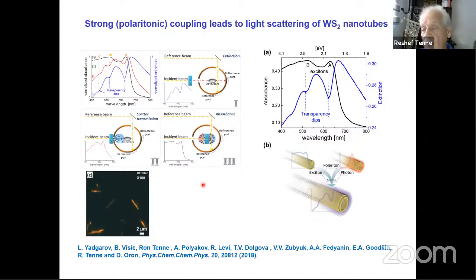As you know, thick 2D materials do not luminesce, but they scatter a lot of light, and we can see this light scattering by forming a polariton. This is a study that was started by my former student Lena Yadgarov, and you see the polariton. If you compare the absorption spectrum of these nanotubes in solution to the extinction spectrum, you see that there is